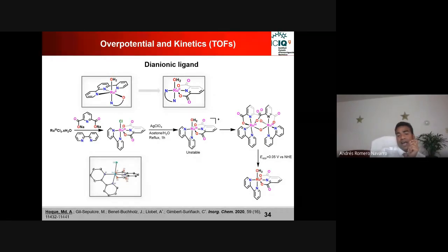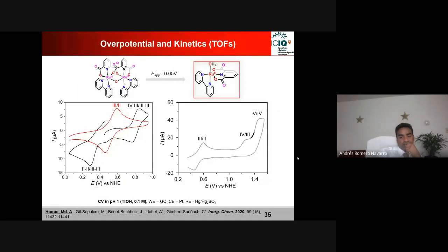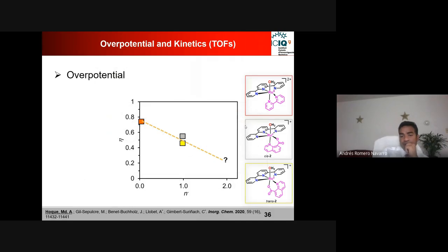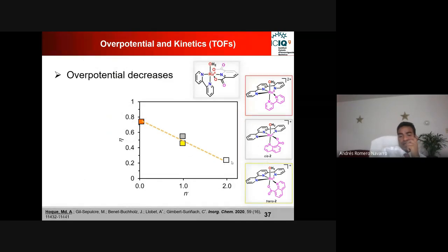So you can see that the unstable compound was in the ruthenium-3 oxidation state, but when you have this ruthenium-2, it's relatively stable. And then we checked their electrocatalytic property, and again I'm saying that this 4,5 redox couple is responsible for water oxidation. We calculated this overpotential, and it is coming at 0.24 volt now. So if you look at this graph, we have reduced this potential approximately 300 millivolt with this catalyst. And as you can see, it's a much lower overpotential for the system.